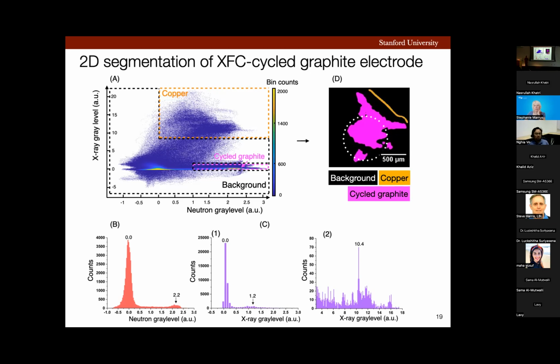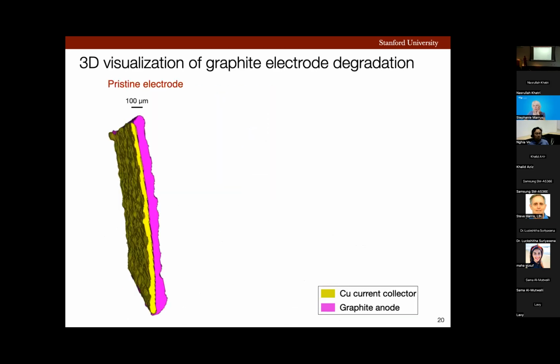Now these are 2D images of a 3D volume. Then I stitched them together to look at the depth of graphite electrode degradation. Here I'm showing a 3D visualization of the pristine electrode, where yellow corresponds to the copper current collector and pink corresponds to graphite. And both these strips are on top of each other with no sign of lithium plating.